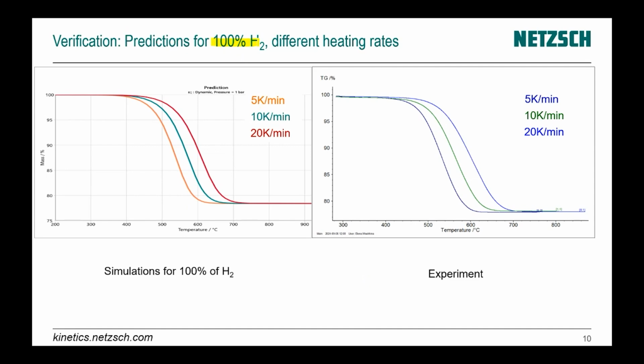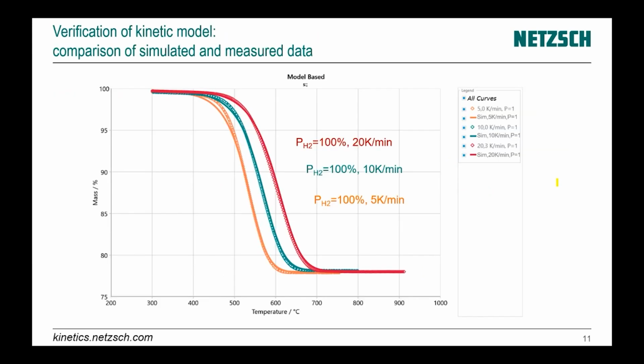Predictions were done for pure hydrogen for the heating rates 5, 10, and 20 K per minute. These data are simulation, and they were not present in our data for the analysis, so they will be used only for verification. And now we did an experimental measurement in pure hydrogen, again for 5, 10, and 20 K per minute. After that, we compare experimental data and simulated data for pure nitrogen, sorry, for pure hydrogen.